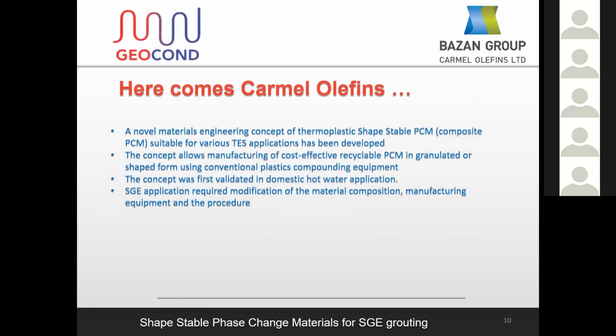And here comes Carmel Olefins. Having experience and expertise in polymer engineering, Carmel Olefins has developed a novel concept allowing cost-effective, recyclable, shape-stable phase change materials in granulated or shaped form to be manufactured using conventional plastic compounding equipment. The challenge was finding a way to achieve the desired balance of properties while increasing PCM content to above 70%.